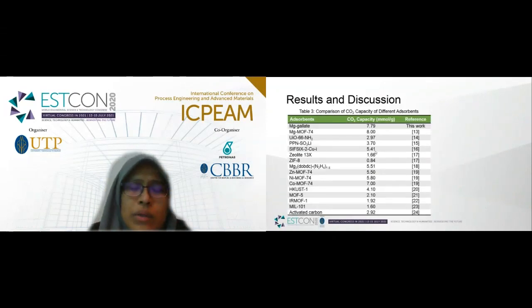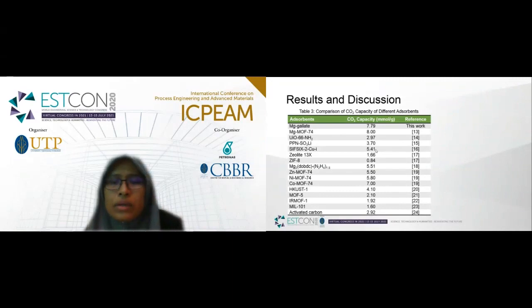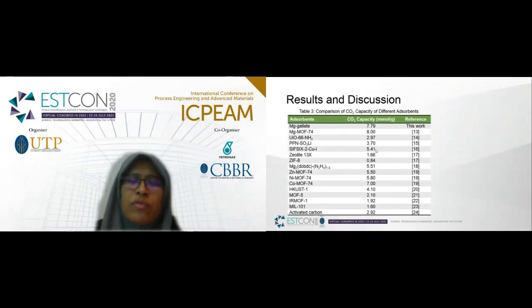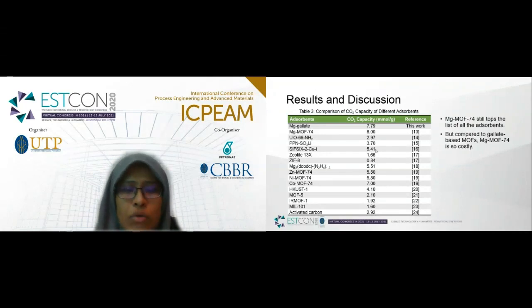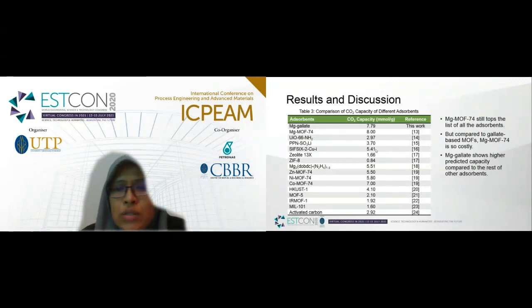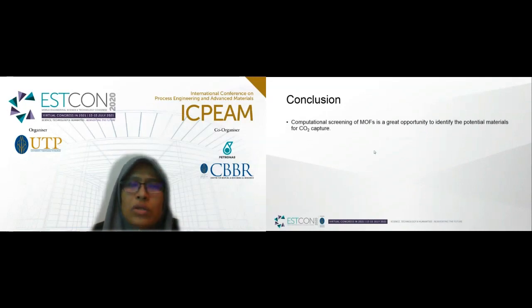Since experimental results on the adsorptive separation of CO2-CH4 using Mg-gallate are not available in the literature, the predicted capacity is compared with other adsorbents in previous experimental work as shown in Table 3. In terms of CO2 adsorption capacity, Mg MOF-74 still tops the list of all the adsorbents. However, when compared to Mg-gallate, Mg MOF-74 is so costly. Nevertheless, Mg-gallate shows higher predicted capacity compared to the rest of the other adsorbents. Lastly, the conclusion is that computational screening of MOF is a great opportunity to identify potential materials for CO2 capture.